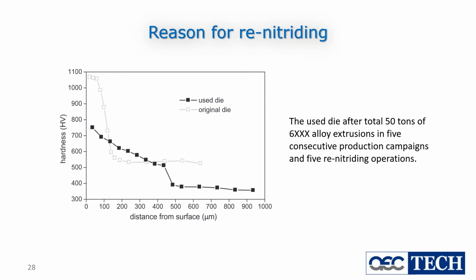This is another graphic. This is showing the difference between a used die and an original die. The die, when it comes in, has got that nice hardness profile we show. But with use in the press, with numbers of times through the die ovens, those nitrogen atoms near the surface may not move as fast at 800 degrees Fahrenheit in a die oven, but they move. And the ones that go out the surface are lost forever. So this will drop down. And this happens to the dies in use. And this is why it's important we re-nitride them. We push that back up.